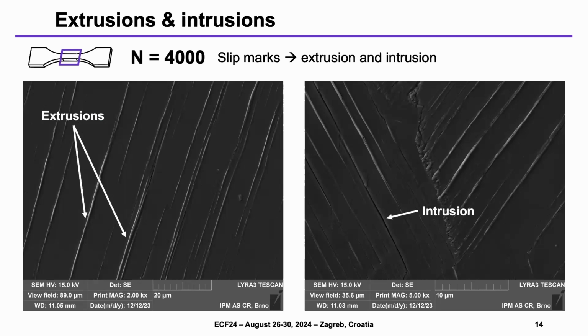As you can see in the left figure, there are some extrusions. We can say that these are extrusions because they are a brighter strip of material, because they protrude from the surface. And close to some extrusions, there are also some intrusions. In this case, the material appears darker compared to the surrounding material because, let's say, the material entered the surface. These kinds of intrusions are, as I said at the beginning, related to crack nucleation.